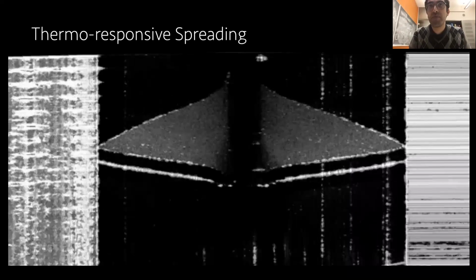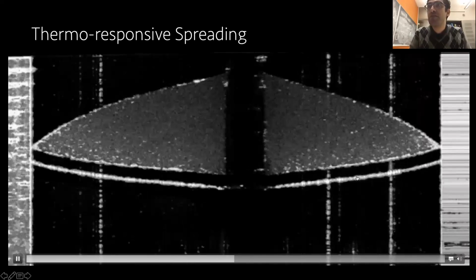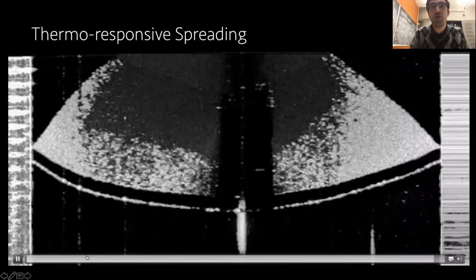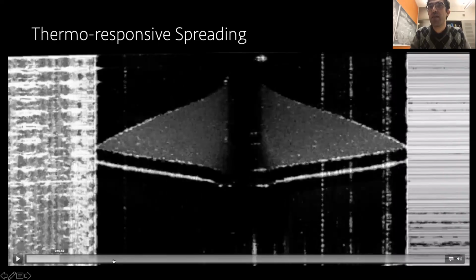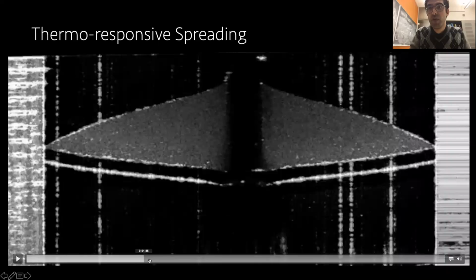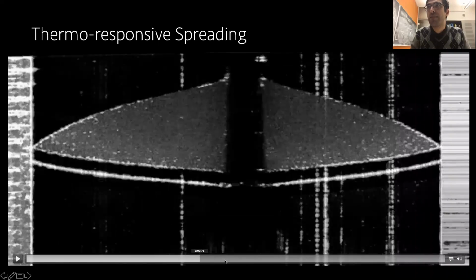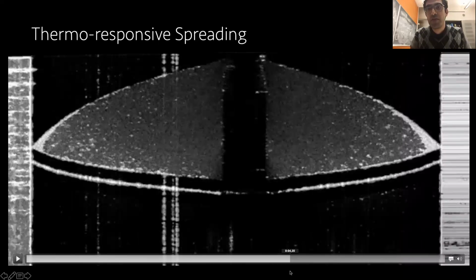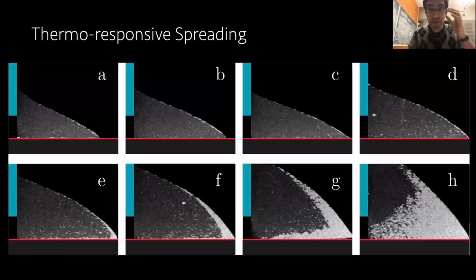So does it happen for the spreading droplet? Yes. Ignore this curvature you see on the bottom, it is an artifact of the method. What I showed you was a thermoresponsive droplet spreading on a heated surface. The droplet is in full Newtonian phase. It stops at some point, and then we can see the formation of gel. So here is a snapshot of the same video I showed you. The droplet spreads, it stops, no sign of gel formation, but then after a while we see that the gel starts to form inside the droplet.